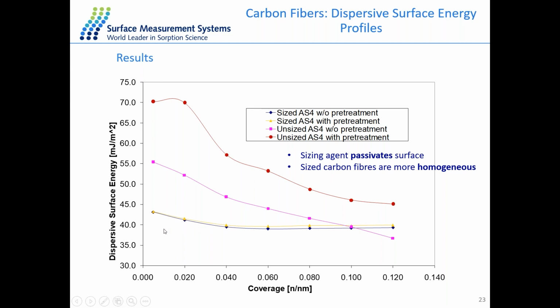What we can understand from this is, first of all, that these samples have a much lower dispersive surface energy compared to our unsized material. What we can also understand from this profile is the surface homogeneity or heterogeneity. Effectively, in this region here at infinite dilution, we are injecting at very small concentrations. So these probes can interact with different areas of our sample, areas of higher energy and higher active sites. And if they interact with higher active sites, then as a result we'll have higher surface energy.